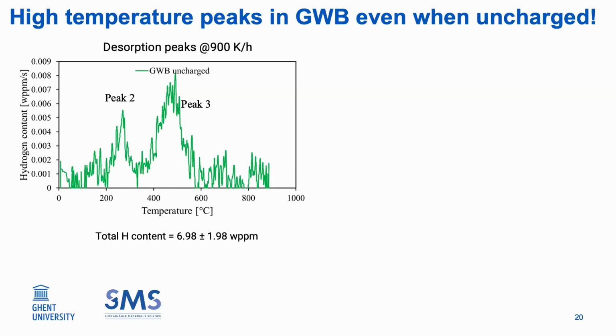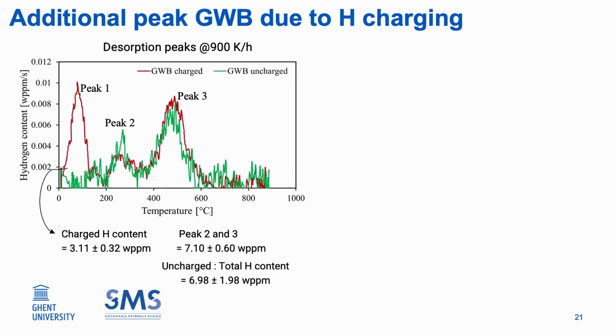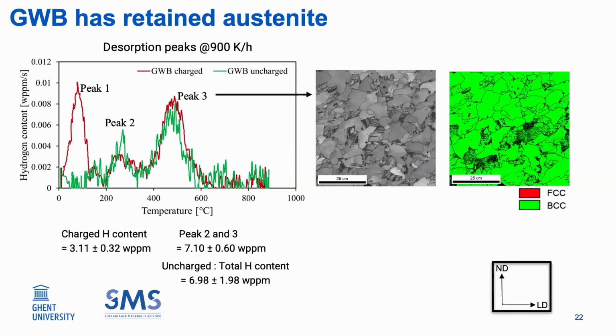Looking closely at this GWB material, we see that even for the uncharged condition, 2 peaks having almost 7 weight ppm of hydrogen are already present. Comparing this with the charged condition, we have an extra peak 1 due to the reversible traps like dislocations and grain boundaries. A deeper look into peak 3 suggests that retained austenite or its interfaces are contributing to this high uptake. Another fact is that since both peak 2 and peak 3 are similarly present in the charged and the uncharged condition, maybe these traps are not being charged by us, but are already present from the production.